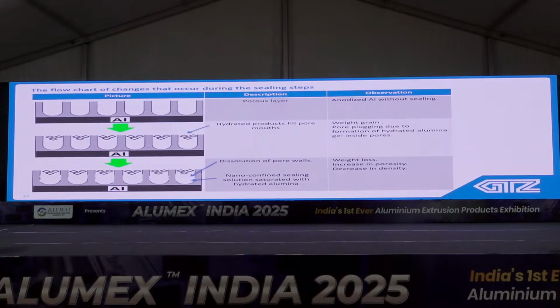So this is the pictorial presentation of the mechanism of sealing. Initially, the first layer is only the anodic layer, then hydrated product fills the pore mouth. Then it usually progresses towards the interior of the pore, and there is some hydrated alumina gel. Then the hydrated alumina gel becomes dehydrated with formation of a pseudo-boehmite structure, and it will then seal the pore and complete the coating sealing system.